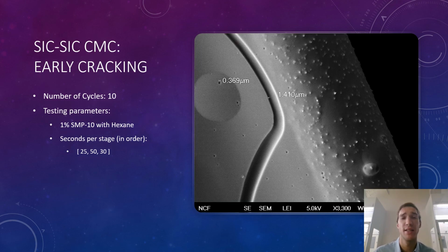Some early cracking, as I mentioned, that 1.4 micron crack. This is another zoomed in image, and you can see that there is some actual buildup happening within that crack. So you can see that it cracked and then has been filled up partially by a subsequent infiltration.